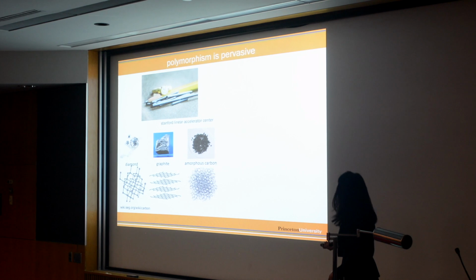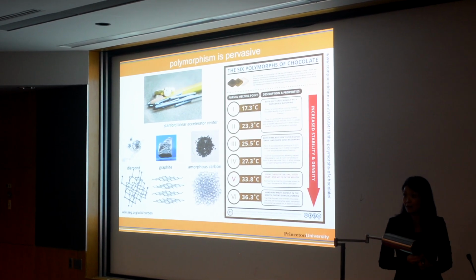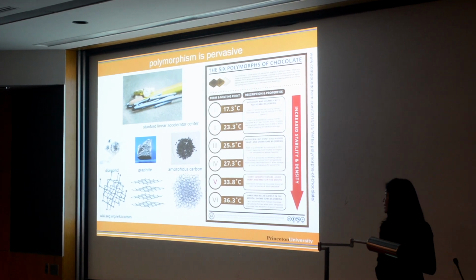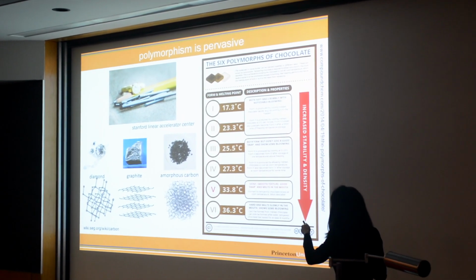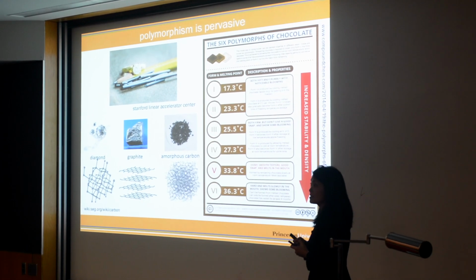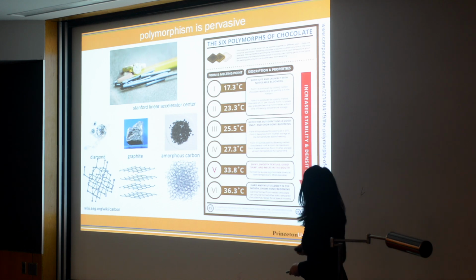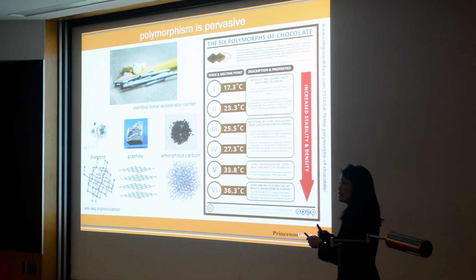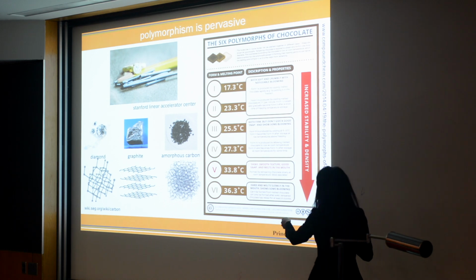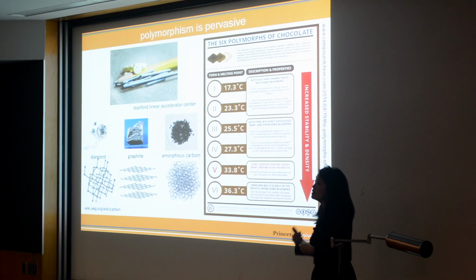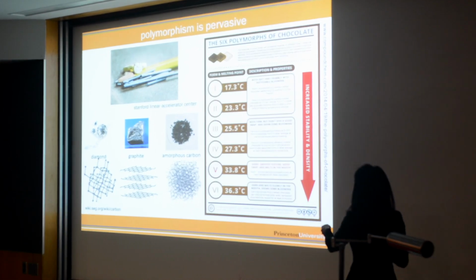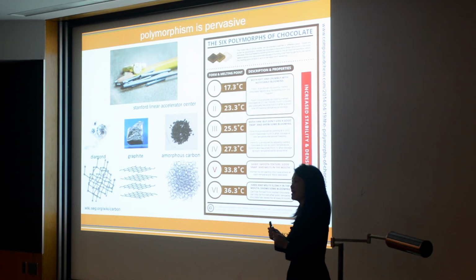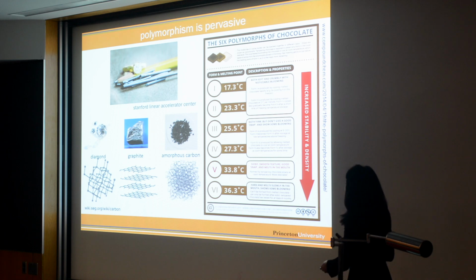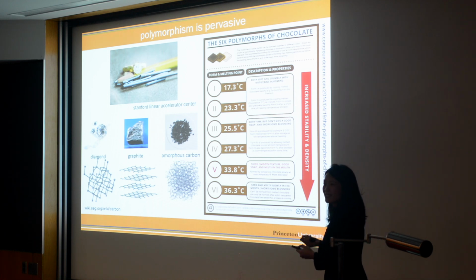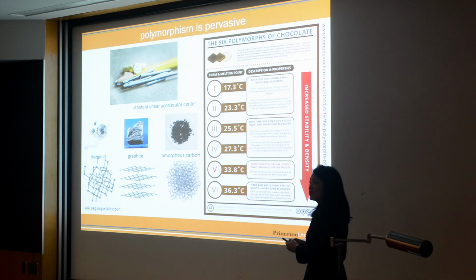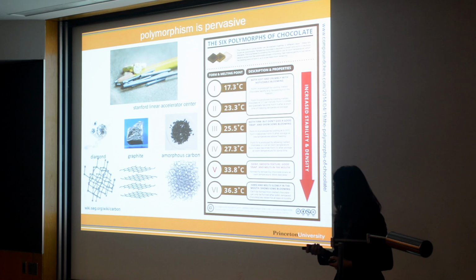And if this is not your cup of tea, you can look at chocolate. Chocolate has a lot of polymorphs. The molecules in cocoa butter can pack in very different ways. And depending on how they pack, you can access different melting temperatures. And so to get the super high quality chocolate, one typically melts and then cools the chocolate down to room temperature and then heats it right to below the melting temperature of polymorph 5. That induces polymorph 5 to grow. Polymorph 5 is the one that gives you this shiny, smooth texture and this snap that everybody likes when they eat chocolate, right? Of course, accessing other polymorphs are okay, but the chocolate doesn't taste as good. So being able to select the right polymorph and getting to the right polymorph becomes very important.